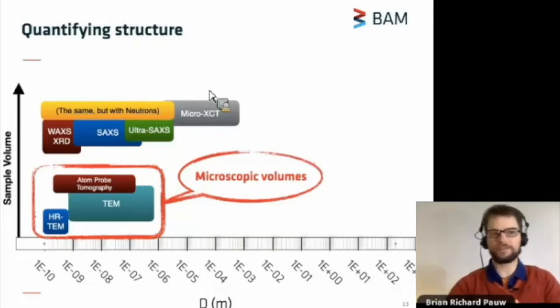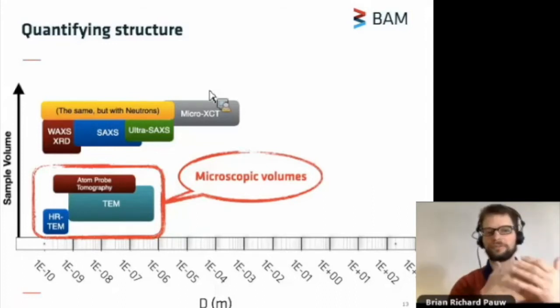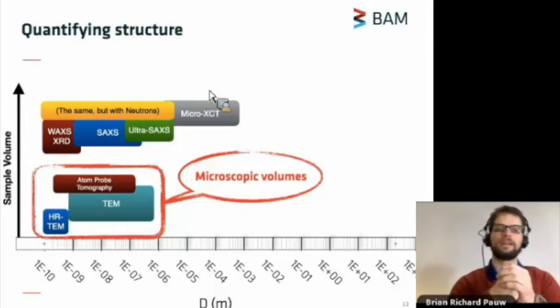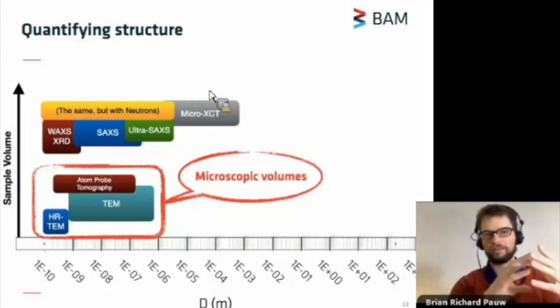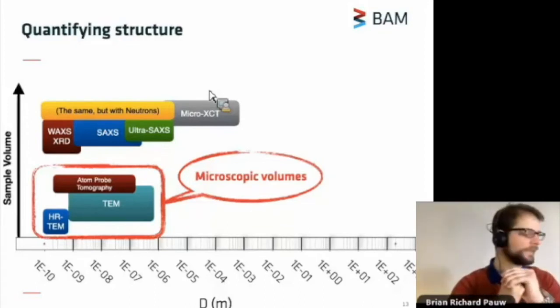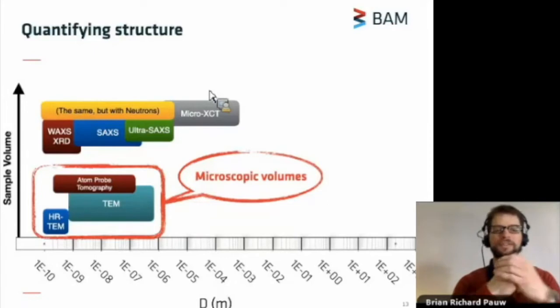Well, two big differences. One is the contrast that you're seeing. So X-ray techniques show the contrast of the electron density of the atoms. Neutrons show the contrast of the radius of the nuclei of the atoms, and this varies a little bit differently than the electron density. The second big difference with neutrons is that everything is an order of magnitude bigger.